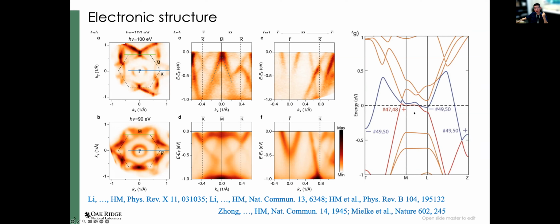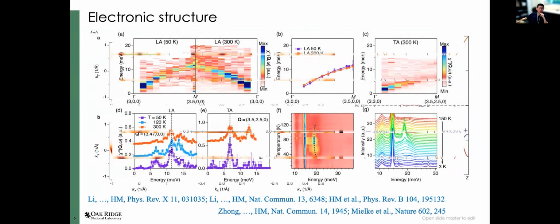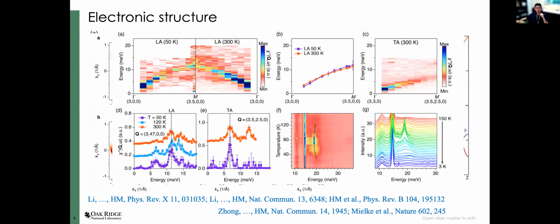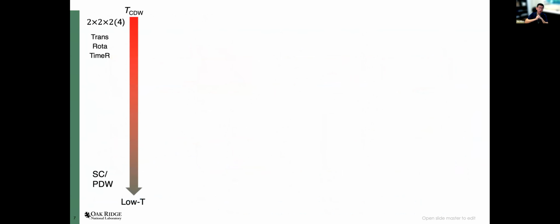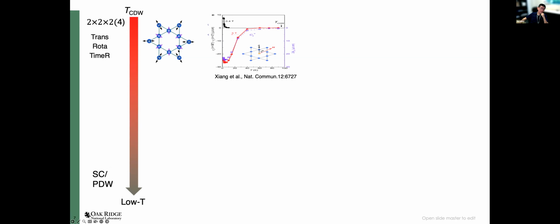And if you check the Chern number of the band, then you realize it's indeed a Z2 topological superconductor. Of course, we're trying to understand the CDW in the system and what drives the CDW in this interesting material. But nonetheless, here's a summary of those systems, and people do find all kinds of symmetry breaking. Because of the formation of the CDW, you break the translational symmetry. And we also point out, based on our X-ray data, that because you form a 3D CDW, 2x2x2 or 2x2x4, you can also break the rotational symmetry. This is confirmed by transport measurements.